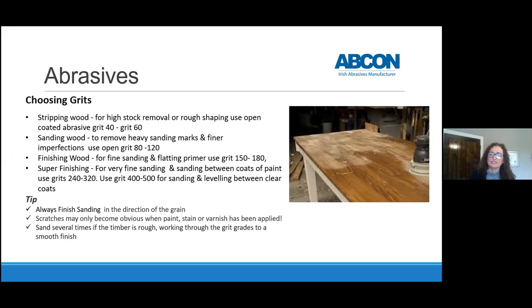So stripping wood, for high stock removal or rough shaping, you can use an open coated abrasive grit 40 or grit 60. They're obviously very coarse. If you're sanding wood to remove heavy sanding marks and finer imperfections, you might go to grit 80 to 120. Finishing wood for fine sanding and flattening primer, you might use 150 to 180.